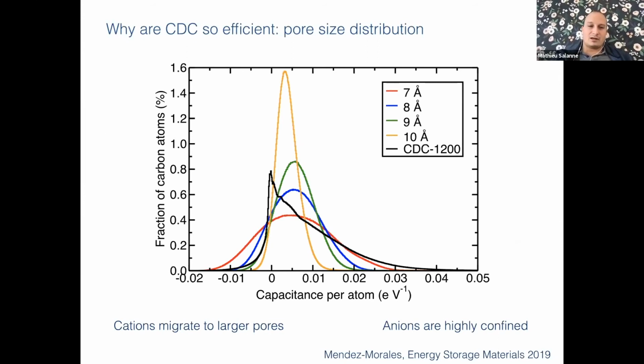So you have some carbon atoms which have a strong negative charge. And this is something we do not see in the complex nanoporous carbon. And in fact, on the left, the complex nanoporous carbon has the same distribution as the 10 angstrom pores. And so what happens here is that, when you have a positive electrode, you want to accumulate anions, but you still have some cations.